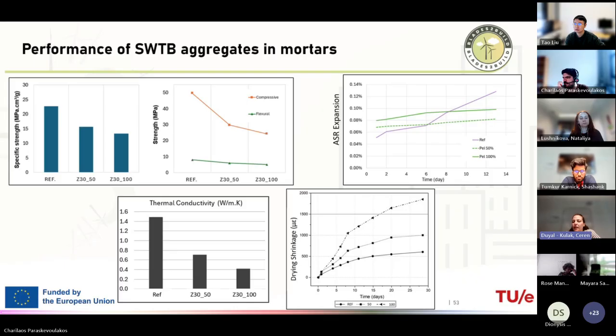When we check the alkali silica reaction possibility, we see that the artificial aggregate replaced mortars performed better than the reference because of the cement paste coating around the waste. And when we check the drying shrinkage, we see an increase of the shrinkage with the increase of the dosage of aggregates. However, it is comparable with other artificial lightweight aggregates, as I checked from the literature.